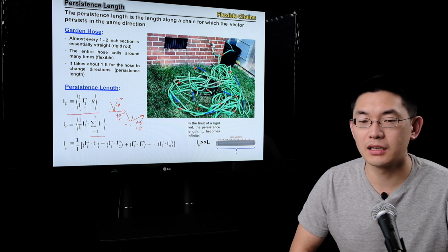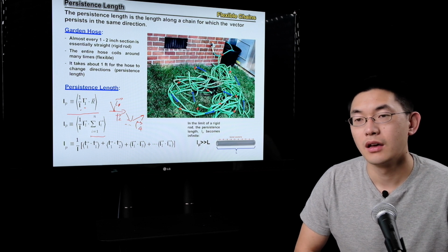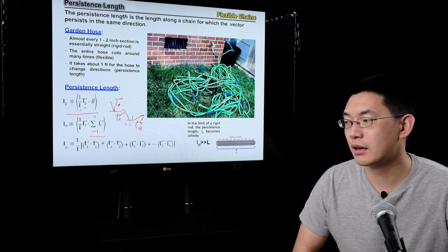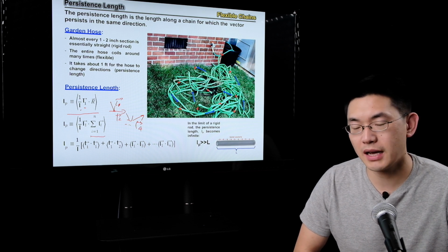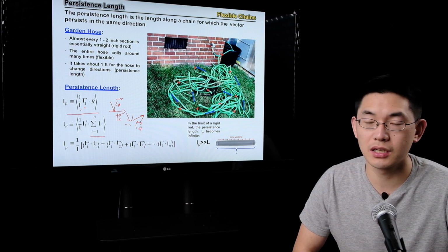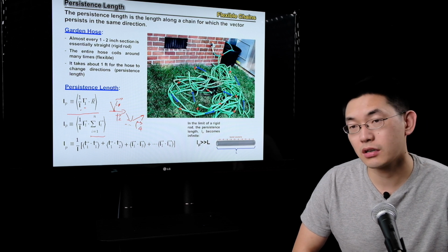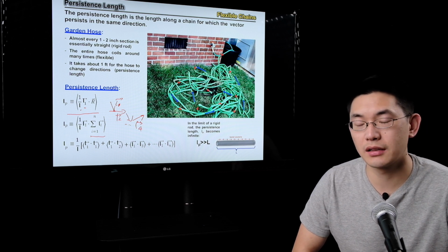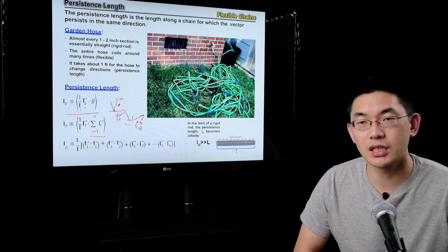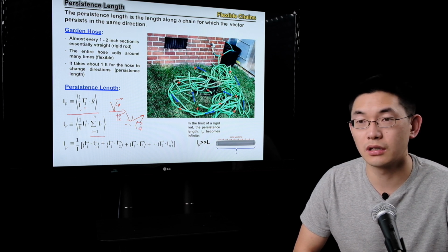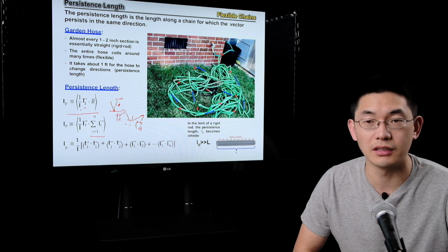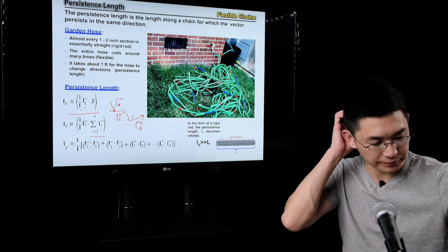You could also compare other, more rigid polymers, like our group's research on a class of polymers called semiconducting polymers. They're made of an aromatic backbone, which makes them more rigid. Their rigidity is typically 20 times that of polystyrene. Another example that people always talk about is the DNA molecule. Those are molecules made up in our body, and they are very rigid as well. Their persistence length can be up to 200 nanometers, which is hundreds of times higher than polystyrene. Quite amazing how rigid these are.